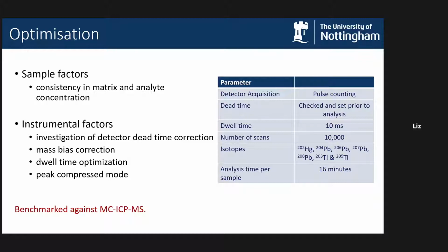So for the internal correction, we teed in a 2 microgram per litre solution of thallium into the sample line. So we could use the fact that its isotopic masses of 203 and thallium-205 were very close to the lead isotopes. We could use those as a proxy for continuous monitoring of mass discrimination in individual samples.